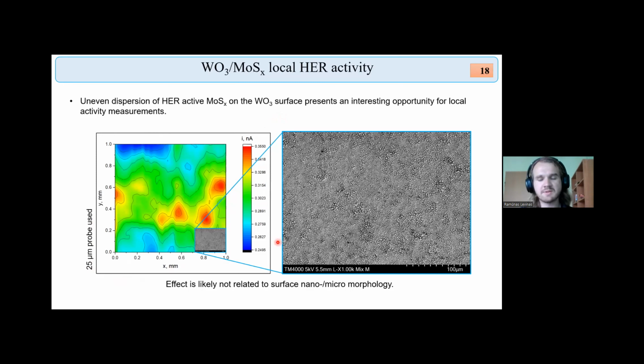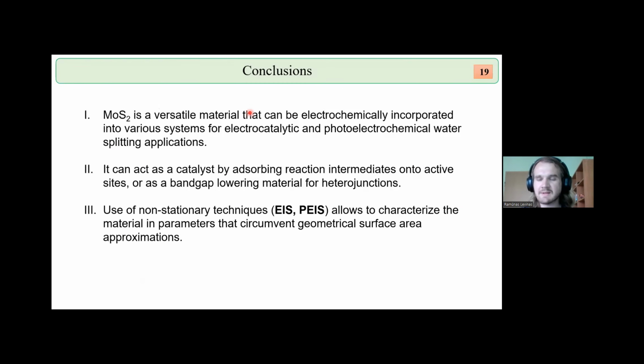But by comparing this to surface morphology, we cannot really relate this to any micro or nanostructures, because as can be seen, this small spot represents this entire piece of surface morphology, and the microstructured nodule surface is even smaller than that. So these large structures could be related to the topography of the sample, if it is very uneven, and here maybe some profilometry measurements could help, because profilometry does show larger topographical information, or there could be some macro distributions of molybdenum sulfide within the film. So this may be a potential avenue for more research. That concludes my data on the characterization of these samples.